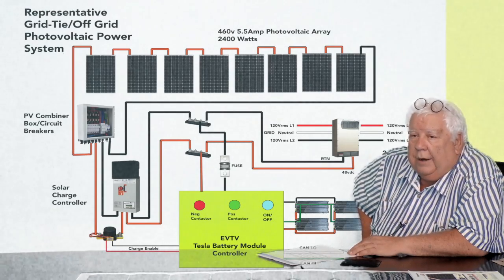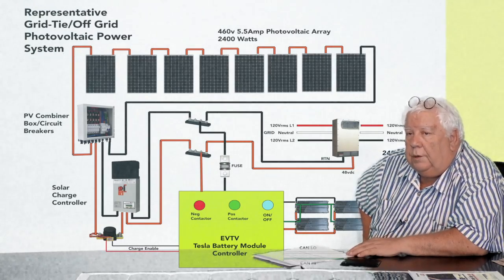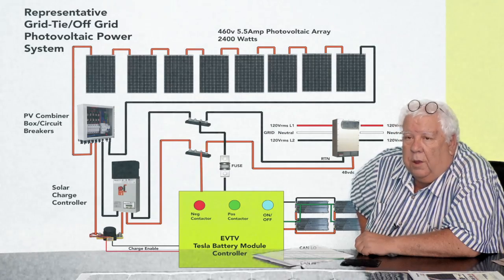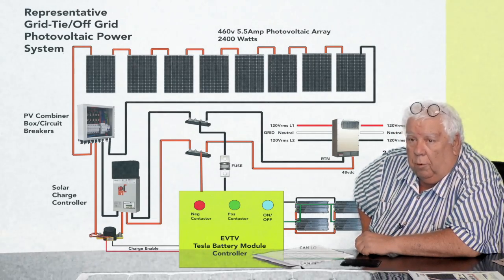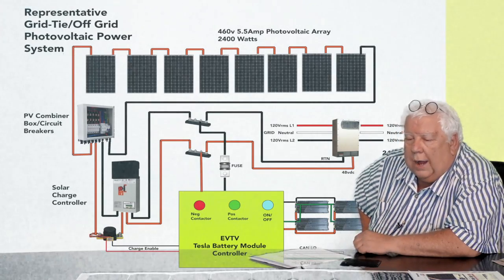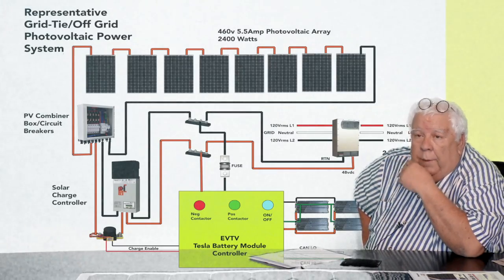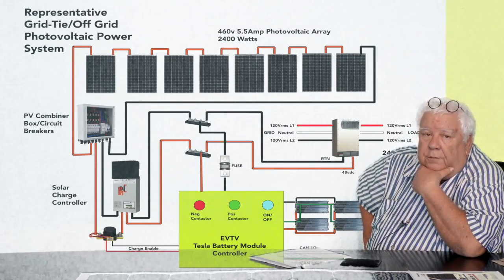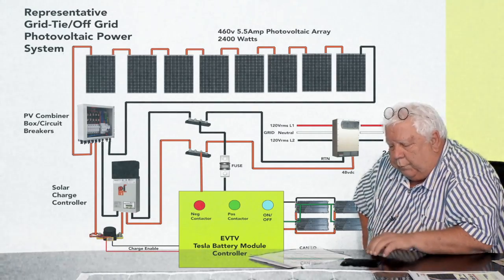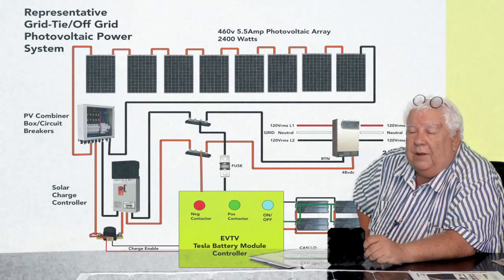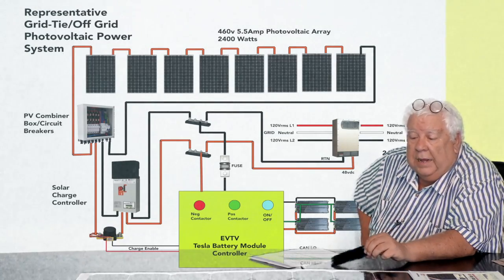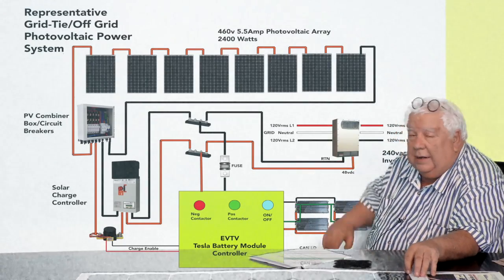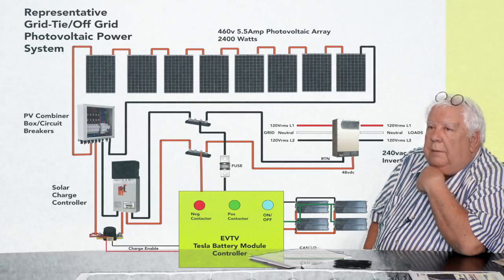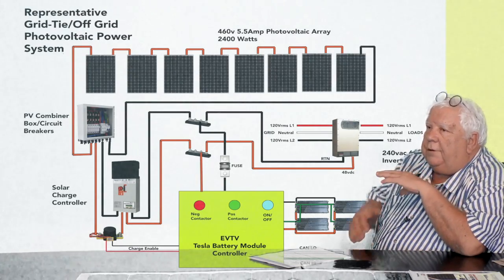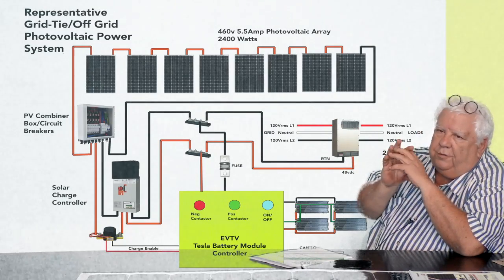And so in full sunlight, if you measure 300 watts per square meter, you're about 30% efficient, which would be remarkable. Typically, a 300 watt panel today would be about 1.35 square meters of cell area. And in the case of the SunPower Maxeon, 125 millimeter cell, that's about 22.5% efficient. In the case of the Panasonic HIT, it's about 19.7% efficient.